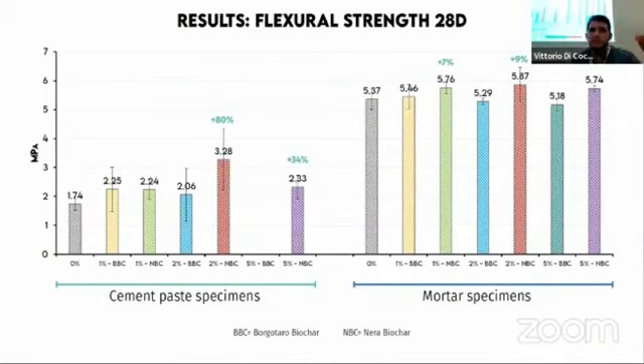Moving to the results, we can see how the biochar particles improve, in almost all the cases, the flexural strength of cement paste specimens and mortar specimens, the best case being when 2% of Nera biochar was used, arriving at an improvement of more than 80%. In the case of mortars, we obtained an improvement of almost 10% with respect to the reference one.